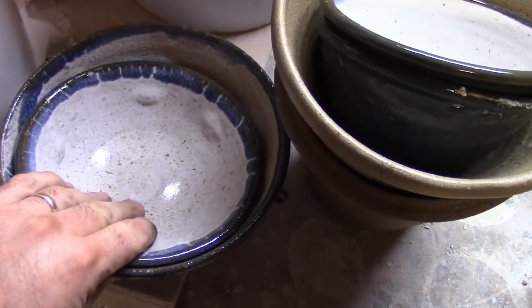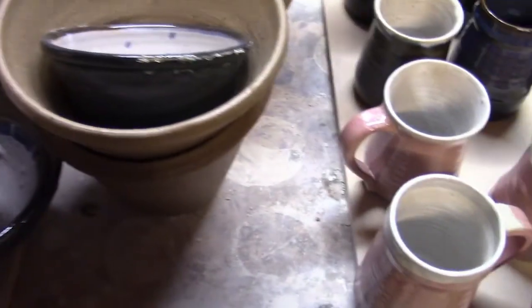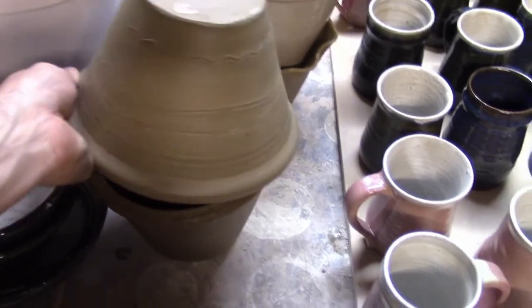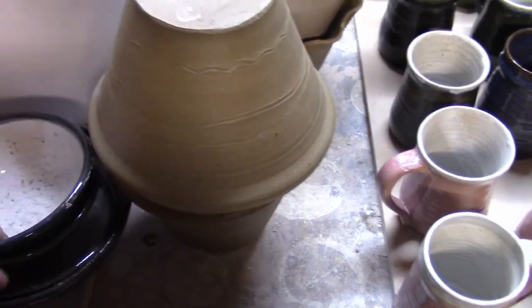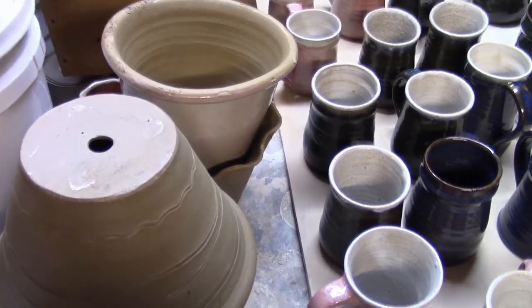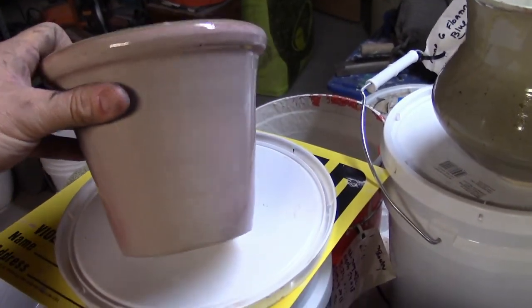Bad bloating because what I had done is I had stacked these flower pots. All the ones that are in big melted messes are still outside. I stack them like this - ones that fit - and I stuck them on top of each other. I think the weight combined with the over-firing just really melted the flower pots. When I didn't stack them they fired okay, but the glaze is heinous - terrible.